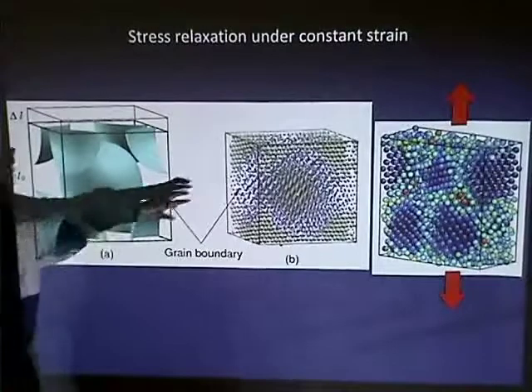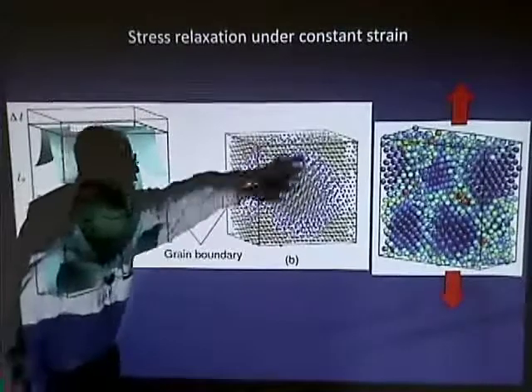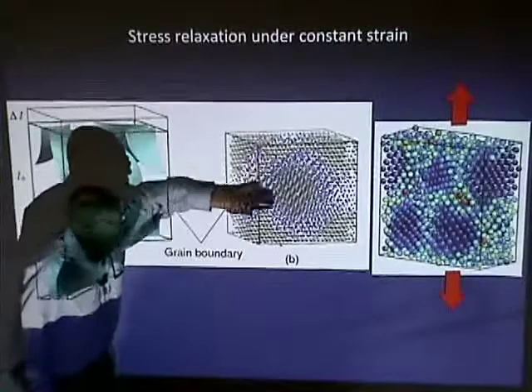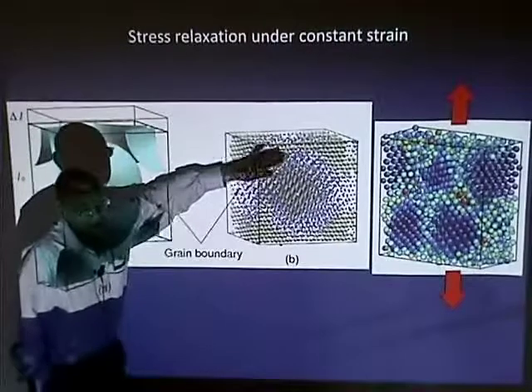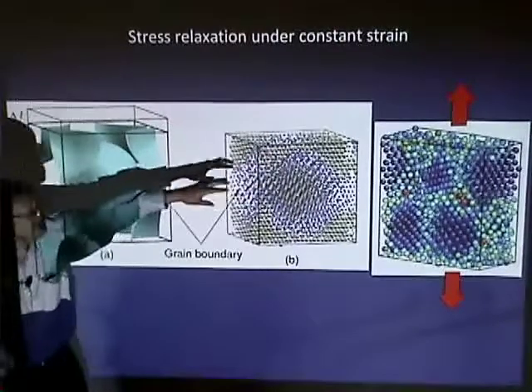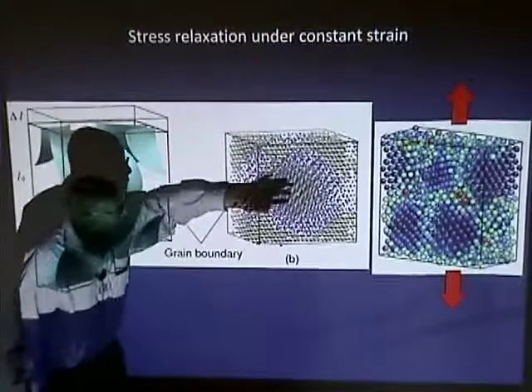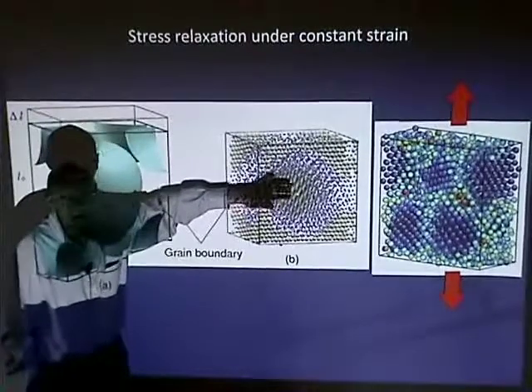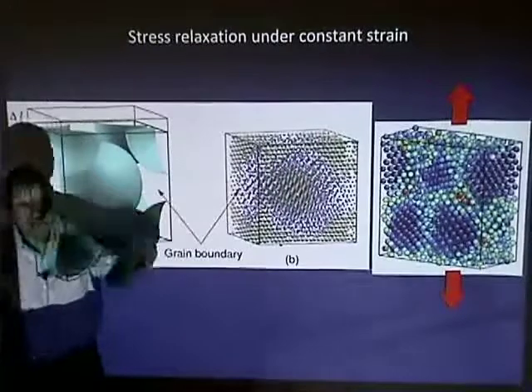So now we have grains inside a simulation cell, and the surrounding material, the matrix, is some kind of grain boundary. The difference between grain and grain boundary is that the grains are highly ordered, crystalline, while the grain boundaries are somewhat disordered, full of misfits.